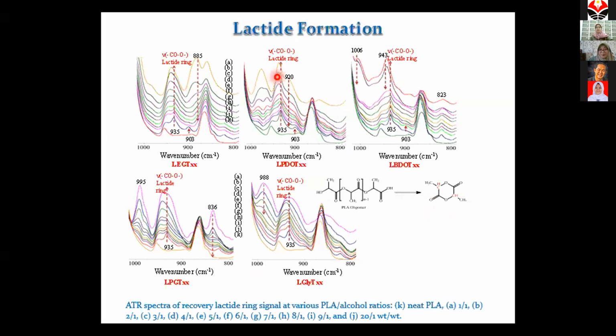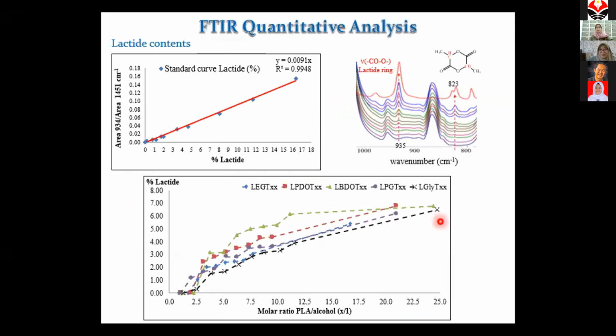And we can control how much lactide we obtain from the reaction. By using FTIR quantitative analysis, we can take the spectrum of the products and the spectrum of a standard solution, make a standard curve, and then look at our products, so we can quantify how much lactide is produced in each system conducted in the chemical recycling process.